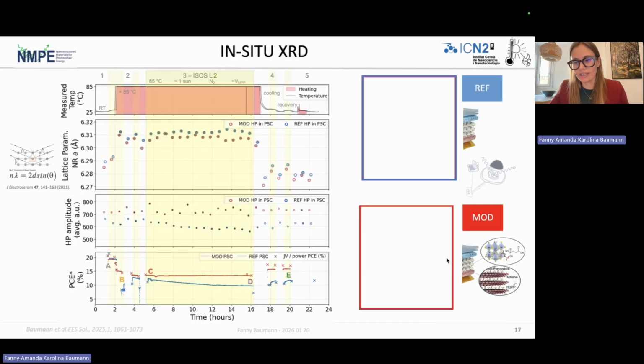Moving on to the in-situ X-ray diffraction, here you can see the modification and the reference, again in red and blue. We have quite a lot of data coming in at the same time. So we have the applied and measured temperature. We have the unit cell length from Nelson-Riley regression, so including all Perovskite peaks with their assignation. We make a rather good estimate of the unit cell length, so the A value. And we also have the average amplitude taken from all the halide perovskite peaks and the approximated power conversion efficiency.